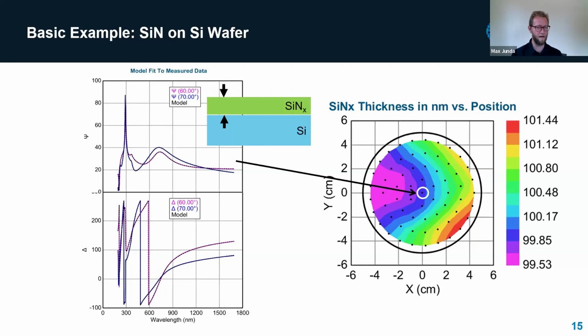So we're showing on the left the model fit to the raw data that was collected by the ellipsometer. Everything fits really nicely. You can see there are some wiggles in the data. And then from that, we're able to determine the silicon nitride thickness. And then on the right, what I'm showing is the example of one measurement spot. I'm giving an idea of how this can be expanded too.